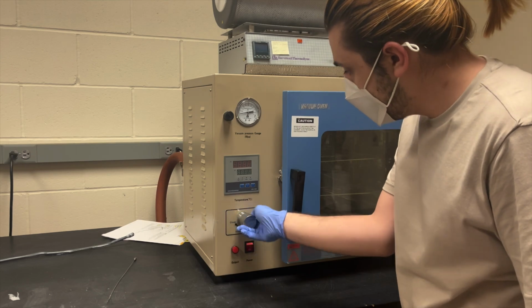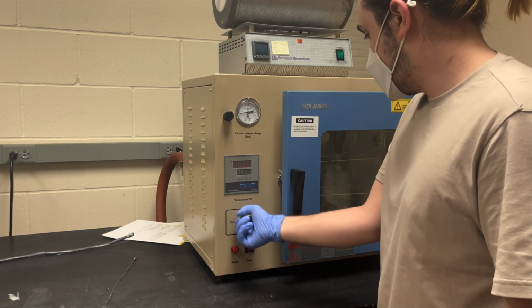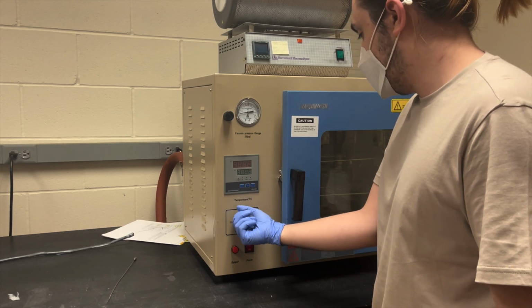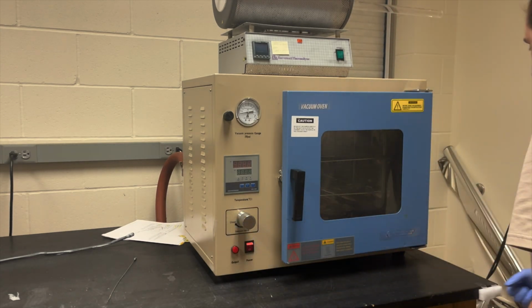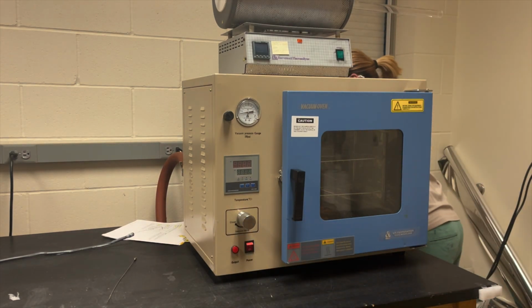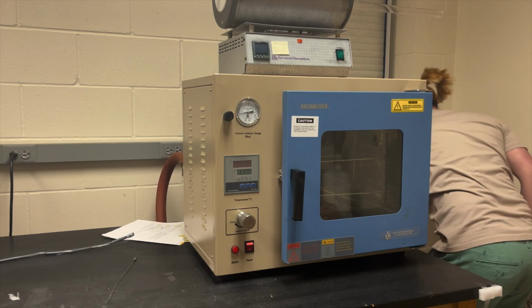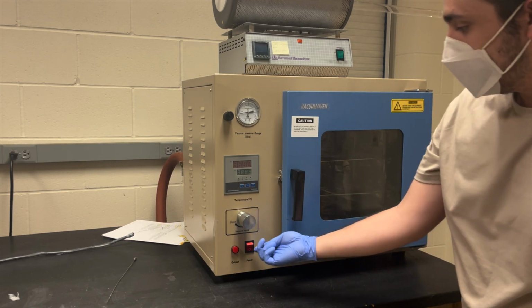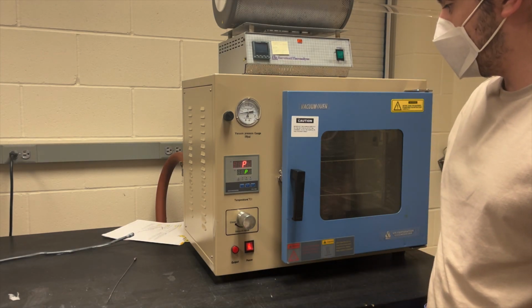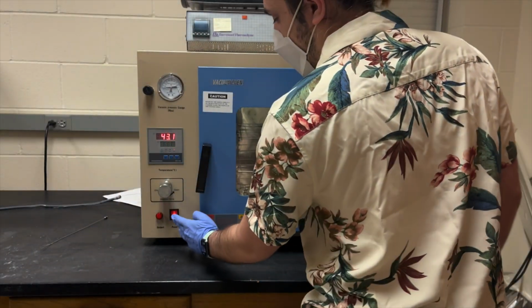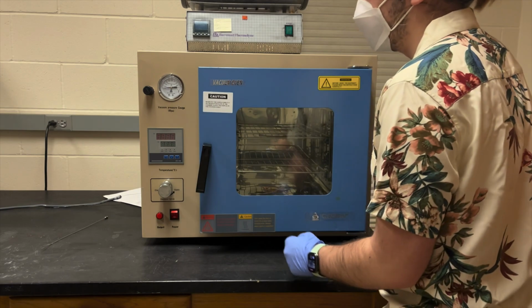The oven is preset to bake at 80 degrees Celsius for 600 minutes, or 10 hours. This will allow all solvent to evaporate and leave behind only the desired materials, and the vacuum will ensure a clean environment free of other particulate. With the flip of a switch, the oven is on, and we let it set for 10 hours. After the 10 hours have elapsed, we will turn off the oven and vent the chamber.